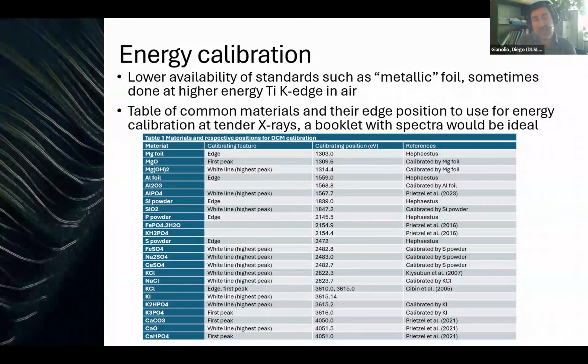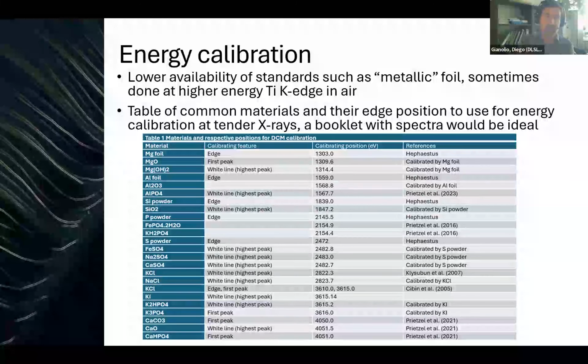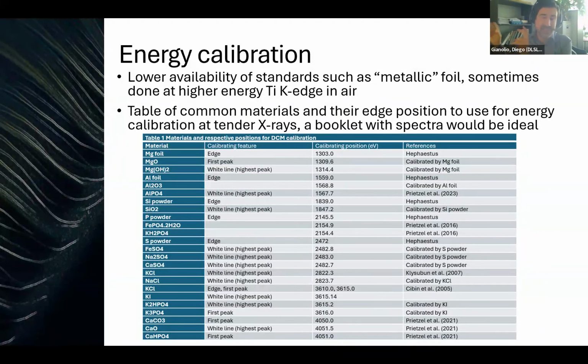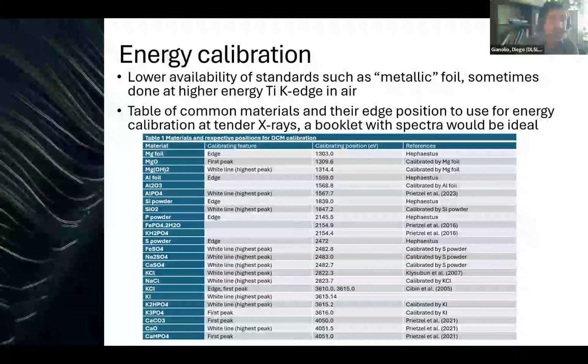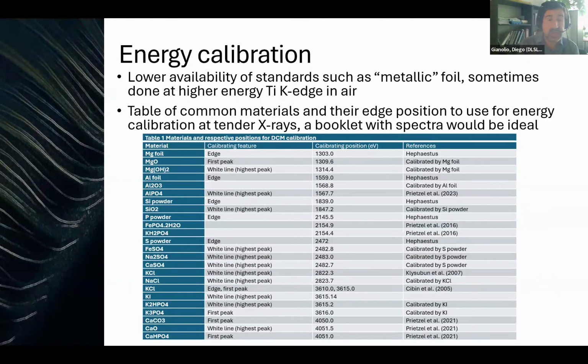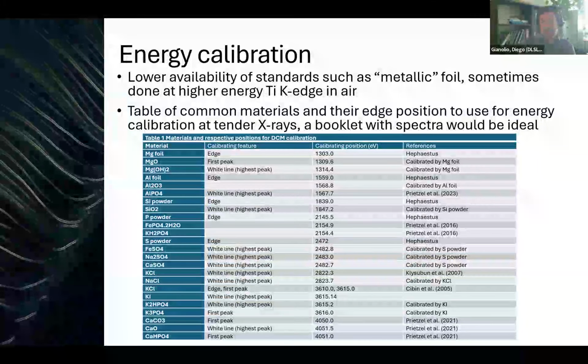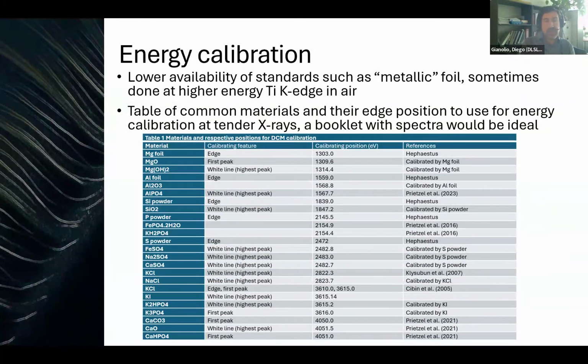And so sometimes, for beamlines that have both the possibility of measuring at tender and hard X-rays, the calibration is done at the lowest possible hard X-ray energy, and then we just move the monochromator and assume that the calibration is maintained. Or we can collect, for example, elemental sulfur that is available in powder, where again the edge is tabulated. But we all thought that it would be useful to have a table with materials that are commonly available with their edge position, that can then be used by any beamline everywhere in the world, where we have this booklet that reports the position of the edge, and we all use this position to calibrate our beamline. So we try to collect some information here.